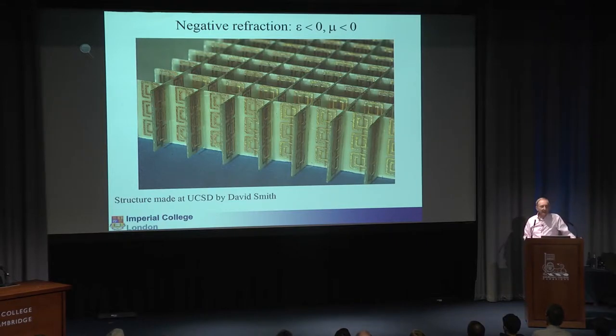You can see this with a child's swing. If you push the swing, it goes where you push it. If you let it swing with its natural frequency, and then the bad brother comes and shakes it at a different frequency, the swing will go in the opposite direction. That's what a resonator does — tune through the resonant frequency and its response is opposite. So this material actually has a negative magnetic response at a certain frequency, polarizing opposite to the applied magnetic field. That is something people have sought for a long time, and there's no material in nature that will do that at the right frequency.